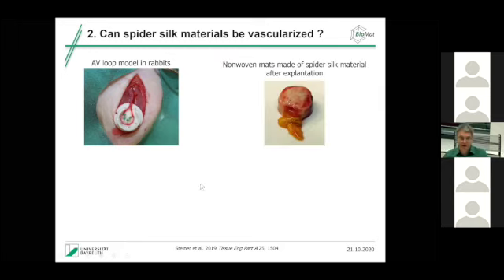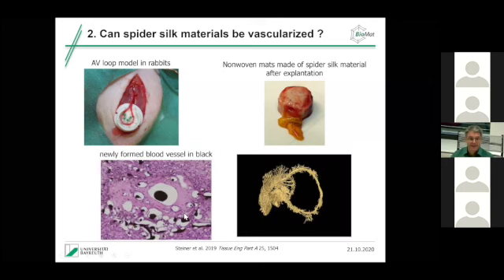And here we tested our spider silk. It's typically in the rabbits for 2 weeks and for 4 weeks. And then it's checked if after 2 weeks or 4 weeks, any new blood vessels have grown. So this is how the explant looks after 4 weeks. And this is what happened. And to our surprise, we see a lot of vessels growing out of the AV loop. And in this histological picture, you see a lot of newly formed blood vessels. All the black dots, these are new blood vessels that have been formed. They're artificially colored to make them visible. These are new vessels that have been formed inside the silk material.